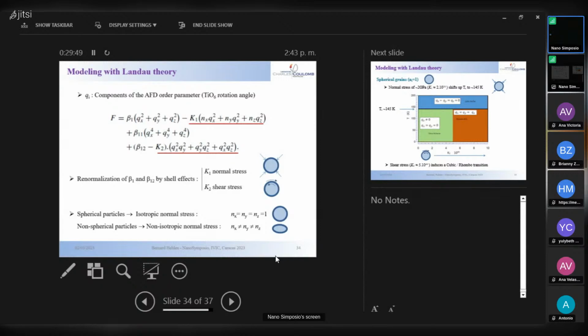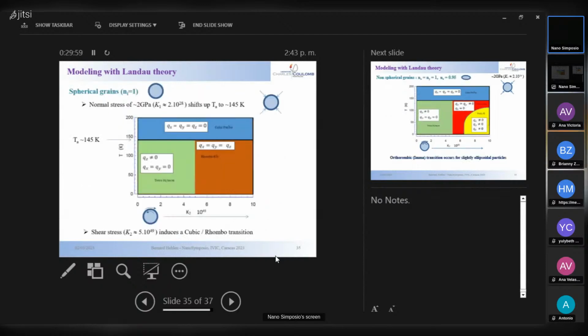So we can play now, using the Landau theory, by varying a shear stress or a normal stress on the grain, and by varying the shape of the grain, whether they are spherical or ellipsoidal. And what we found is this. First, let's take spherical grains. If you have spherical grains, and you apply a pressure in pascals on your sample, and you go into this line where the shear stress is null, you lower the transition down to 145K, which is somehow what we found in the artificial core shell.